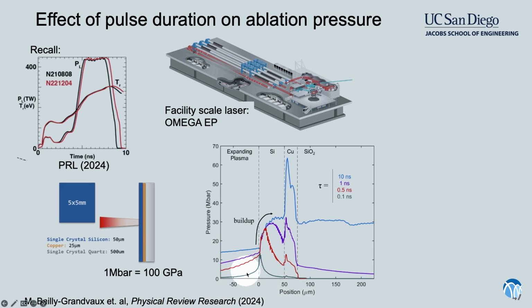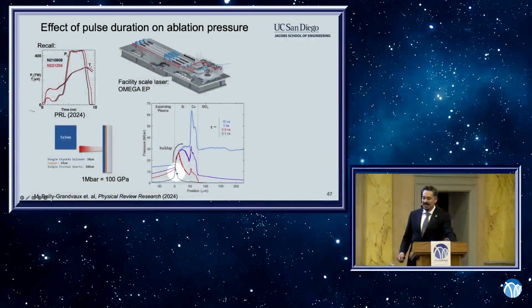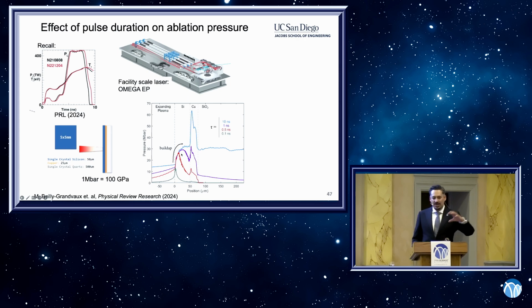Here's the position, as the pressure shock wave moves from the surface through the silicon. Each curve represents a different time scale of the laser pulse that was used. At short time scales, less than 1 nanosecond, you get a very high pressure, but it's not nearly as high as you can get as you make the laser pulse longer and longer. With the longer pulse, here in the sweet spot, about 10 nanoseconds, you get a very large pressure. And that's why people use nanosecond pulses for these ICF schemes.